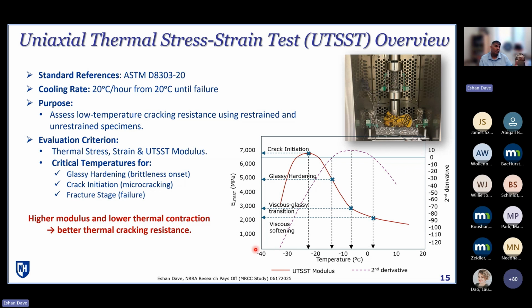Combining that stress and strain history, you are really able to look at what's happening in the evolution of that mixture in terms of how it generates the stresses, at what point it starts to fail, not like a fracture test with a notch, but fail internally, as in how the stresses get so high that the material starts to get damaged throughout and start to break, and eventually this restrained specimen breaks or fractures into two pieces. So using that information, we are also able to extract some parameters that can tell us how these different types of mixtures may behave when it comes to thermal shrinkage or low temperatures. So that's another test that we set up and conducted on these mixtures.